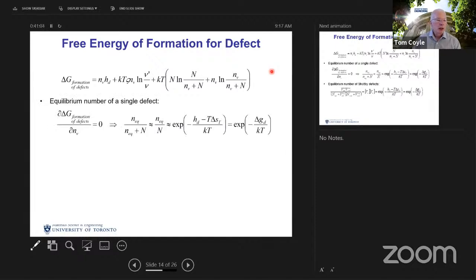And if we want to know what the equilibrium number of defects is, we take the derivative of this with respect to the number of defects and set it equal to 0. Where does the change in this equation with respect to the number of defects find its minimum? With some approximations, we end up with something that looks pretty familiar from thermal chemistry, an exponential that depends on the free energy of formation of the defect over kT.